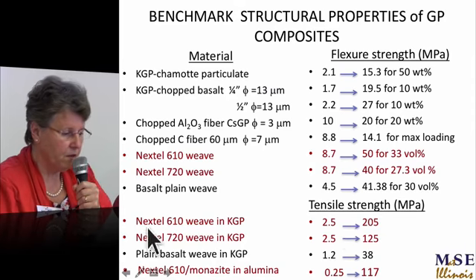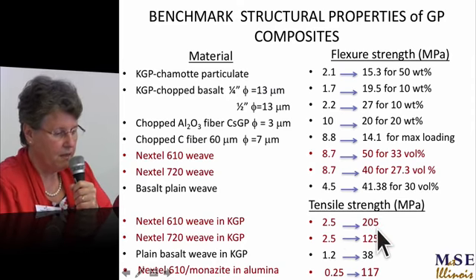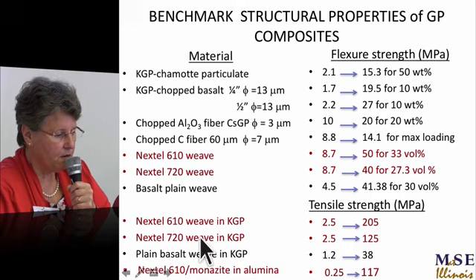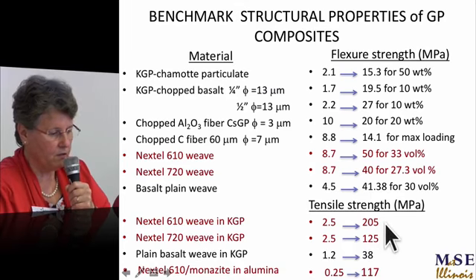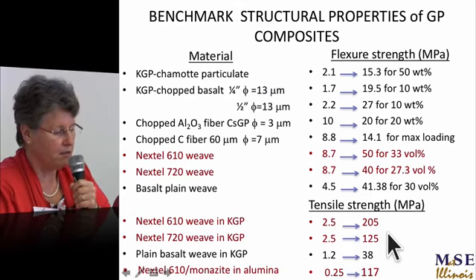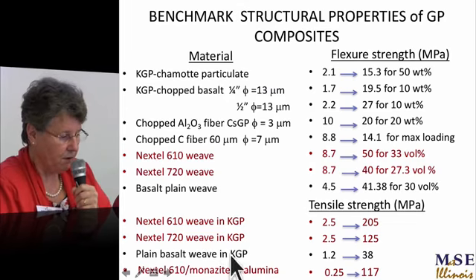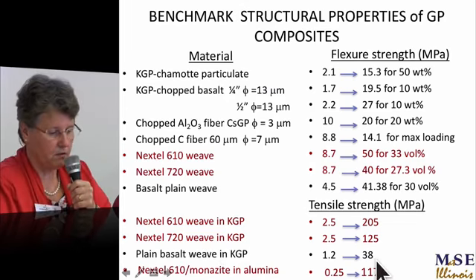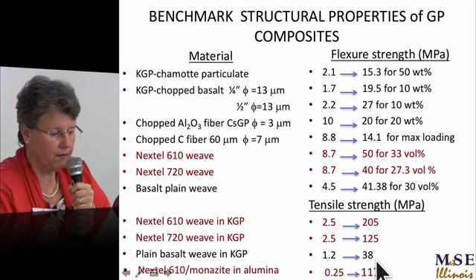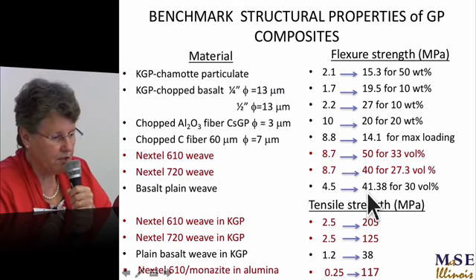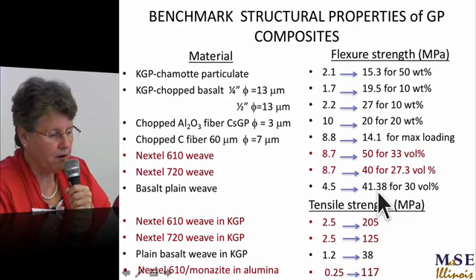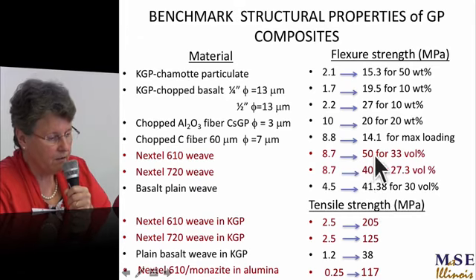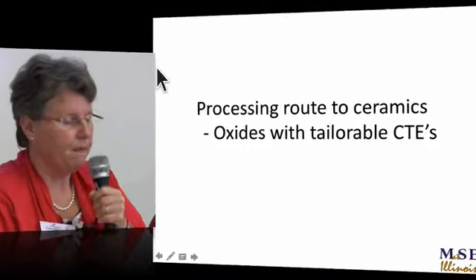But if you use Nextel 610 plus geopolymer, then you can get just as good, if not better. And if you use cheapo basalt, then it's, well, it depends on the basalt. But the flexural strength with basalt is quite respectable: 41 megapascals compared to 40 for mullite and 50 for alumina.